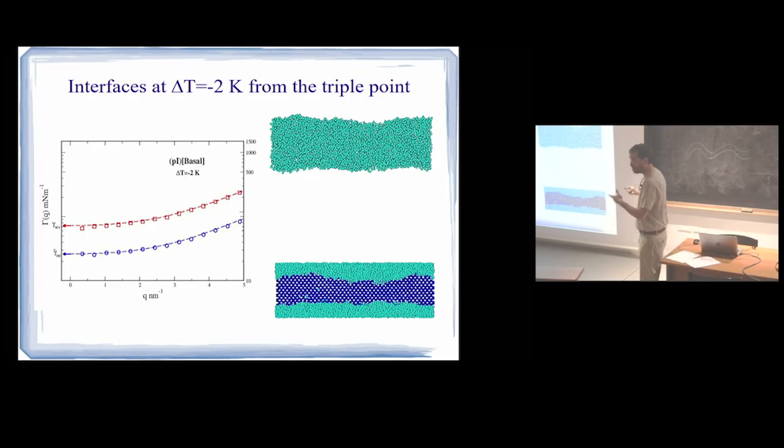It's very large because from this wave vector dependent surface tension, I can see that this interface is rough. It's not smooth. It's rough. It doesn't behave in a way significantly different from this one. It actually has a smaller surface tension. So the amplitude of the fluctuations is larger. Okay, so that's for the two bulk phases, the interfaces separating two bulk phases.